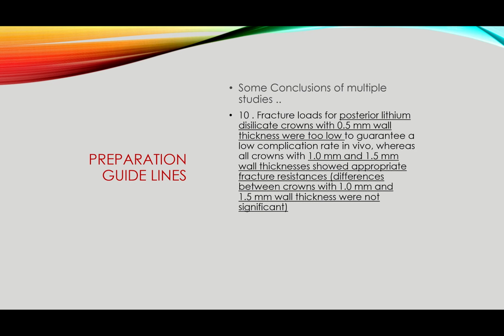Just like the Spear Education recommendation, they said 1 millimeter wall thickness of lithium disilicate. So here it says 1 millimeter to 1.5 millimeter wall thickness of lithium disilicates in the posterior area showed a good fracture resistance. Now differences between crowns with 1 millimeter and crowns with 1.5 millimeter wall thickness were not significant. So 1 millimeter wall thickness for lithium disilicate in the posterior area is good enough, they're trying to say in the conclusion of this study.